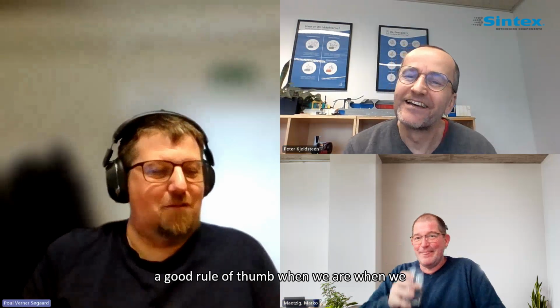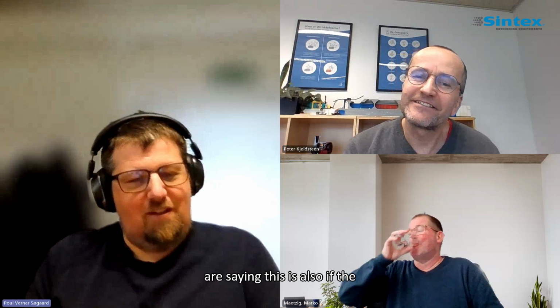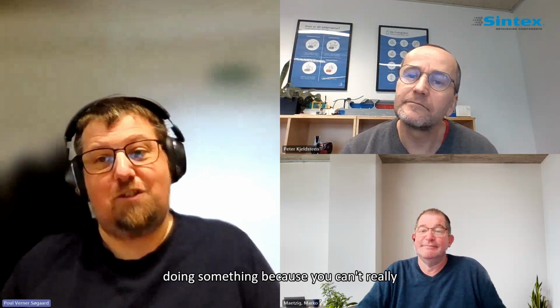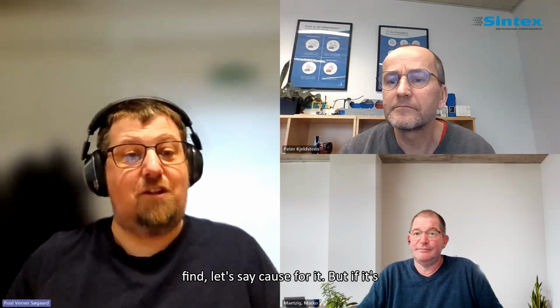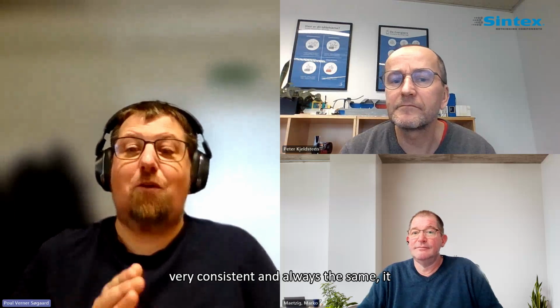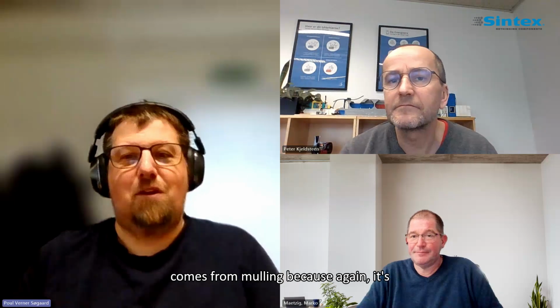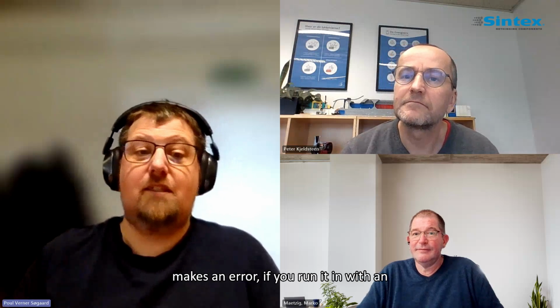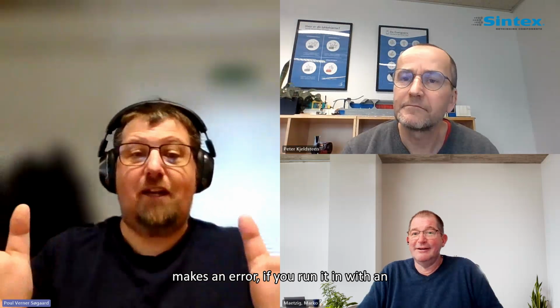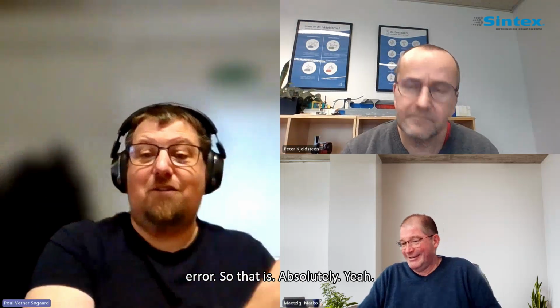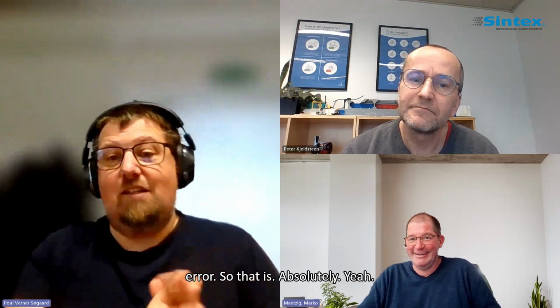A good rule of thumb is also that if the error is random or chaotic, it is most likely the furnace which is doing something, because you can't really find a cause for it. But if it's very consistent and always the same, it comes from molding, because again, it's a very accurate process. So if you run it with an error, it's going to continue making that error. So that is absolutely so.